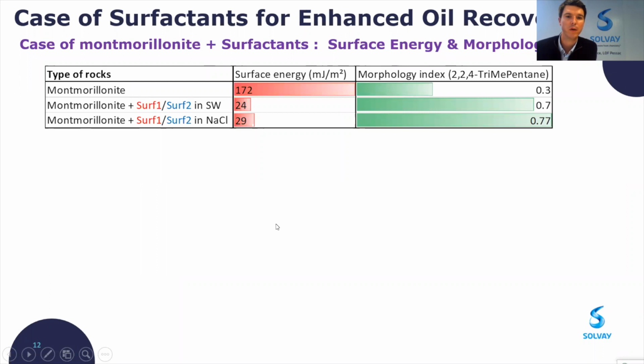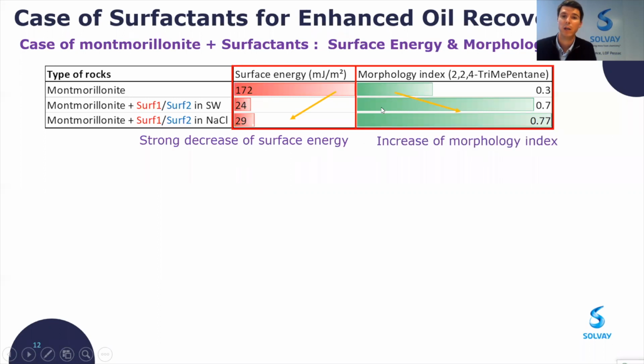So concerning the results for inverse gas chromatography, in the case of montmorillonite plus surfactant, we have measured the surface energy and morphology index. And as you can see here, the surface energy is very high at the beginning on the pristine montmorillonite. But when you adsorb some blend of surfactant at the surface of the montmorillonite in different conditions, in seawater or in sodium chloride, you can see a strong decrease of the surface energy. And concerning the morphology index, inversely, you have a strong increase of the morphology index value.